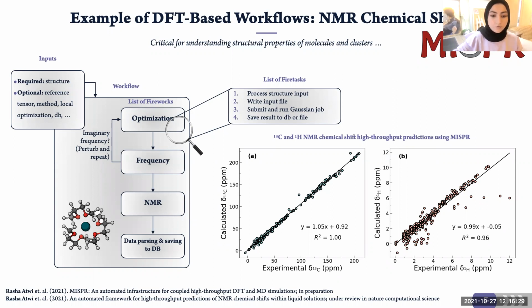Using this workflow, we were able in one project to accurately predict the NMR chemical shift for commonly used organic solvents, mainly the carbon and hydrogen chemical shifts, and we were able to obtain very high correlation coefficients with experimental measurements.